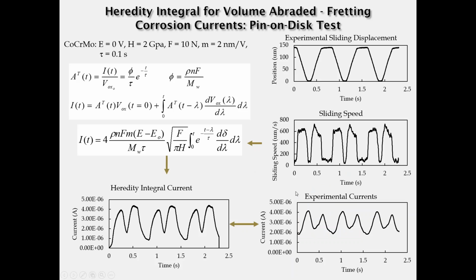And so just to give you an example of how this works, for a pin-on-disc test, we might have sliding abrasion that looks something like this, where we slide and pause, reverse the slide and pause, slide again and pause, and then the velocity associated with that, the dv/dt, is shown here. And then the currents that we measure from that experiment during a pin-on-disc test are at the bottom. But when we take the sliding data and numerically integrate them in this function, this heredity integral, we get this plot of the predicted currents based on this sliding velocity profile.